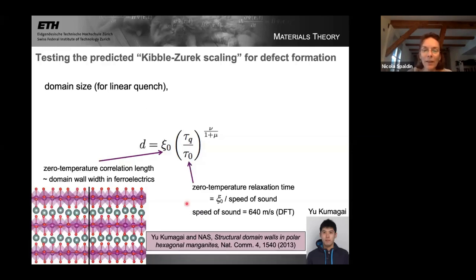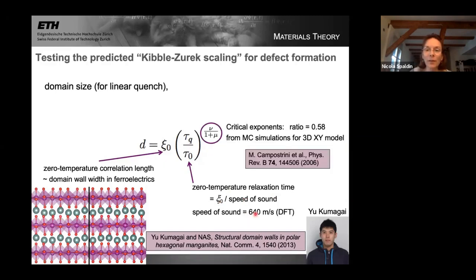The zero temperature relaxation time is the zero temperature correlation length divided by, we approximated it to be that divided by the speed of sound, which we calculated again using density functional theory. The critical exponents, we just took from Monte Carlo simulations for the 3D XY model. This ratio has also subsequently been measured and it's very similar to this value. And the thing that we're varying, tau Q here, is the transition temperature divided by the cooling rate. So we know all of these parameters and we can test the domain size as a function of cooling rate.